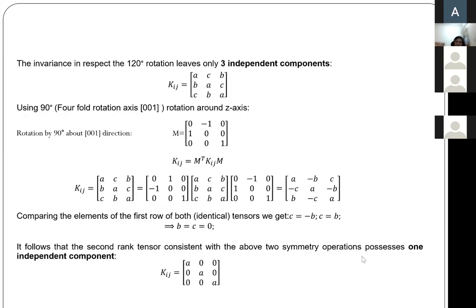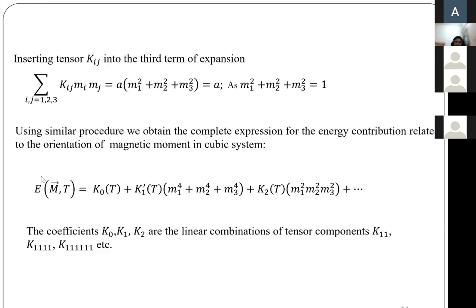Moving forward, we can apply the 90-degree, or fourfold, rotation about the 001 axis. In that case, the rotation tensor is something like this: 0, -1, 0, 1, 0, 0, 0, 0, 1. Applying the same symmetry argument, that K should remain unchanged under this rotation, we end up getting that this will only happen if Kij is just a diagonal tensor with all 3 components equal.